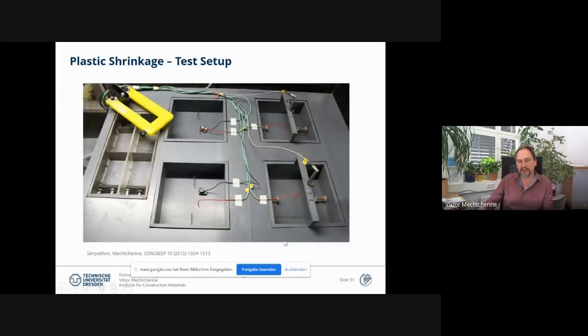Testing plastic shrinkage is obviously quite an interesting case here because we do not have formwork, so the plastic shrinkage occurs right from the beginning. We have no protection for the walls either. In the normal case we do not care about plastic shrinkage in the walls because we have formwork for the first couple of hours, but in this case not. And for the stiff types of concrete we use for 3D printing, this kind of setup is not acceptable because we cannot really place material in such molds without much trouble. So we need to go to another solution.